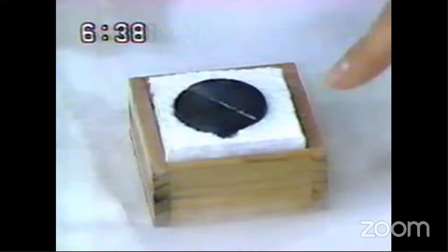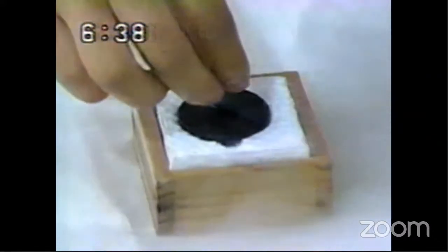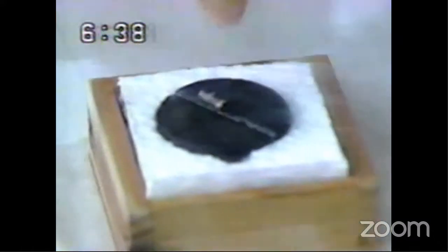For instance, this is a demonstration of how we can use the high-Tc cuprates. For the usual metallic superconductor, we need to use liquid helium, which is very, very expensive. But nowadays, by using a high-Tc cuprate, we can use liquid nitrogen to cool it down. This demonstration video was released around 20 years ago on Japanese TV. The black part is a high-Tc superconducting oxide, which has a Tc higher than 90 Kelvin, much higher than the liquid nitrogen temperature. They cool it down and put the magnet on. This is a magnetic floating effect. Please see the magnet completely floating above the high-Tc material, which pushes up the magnet. This is how the linear motor car runs, using the same behavior.